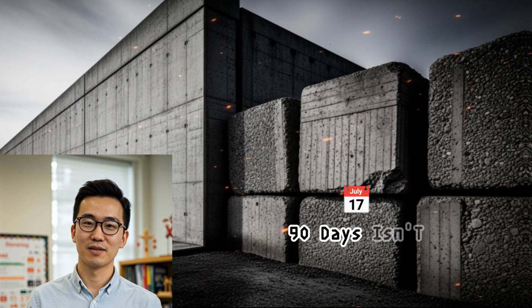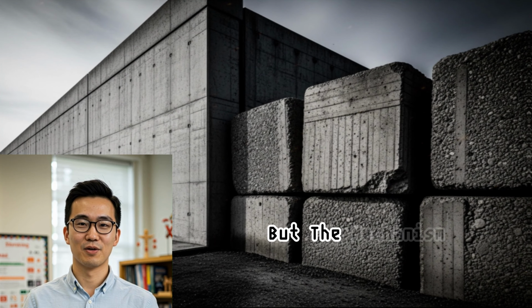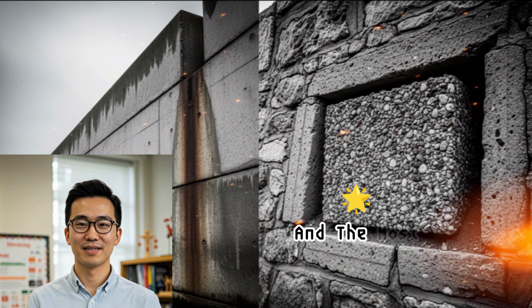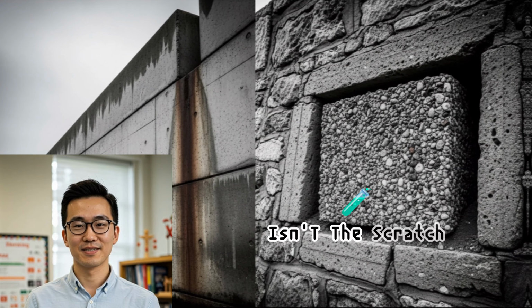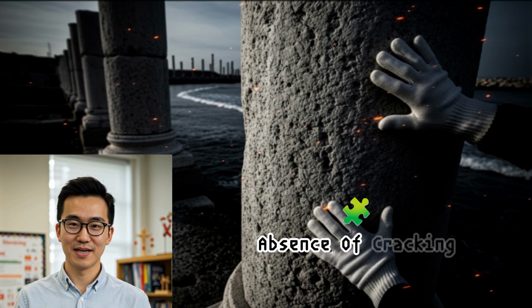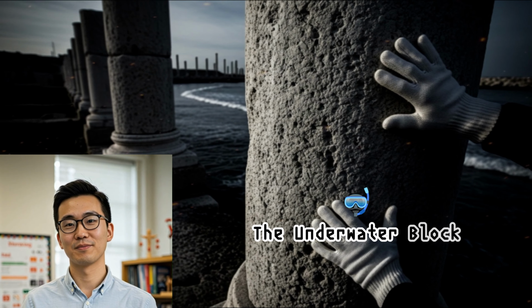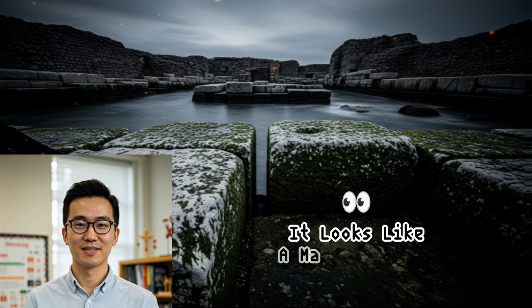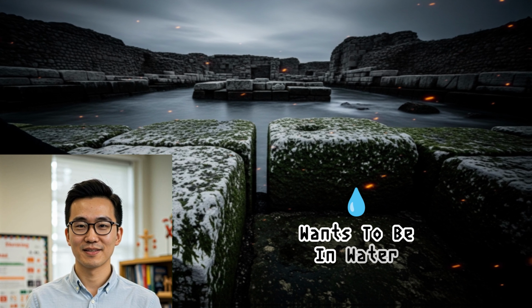These aren't Roman harbour walls. 90 days isn't 2,000 years, but the mechanism is identical. And the most important result isn't the scratch test, it's the absence of cracking. The underwater block didn't just survive immersion, it used immersion. It looks like a material that wants to be in water.